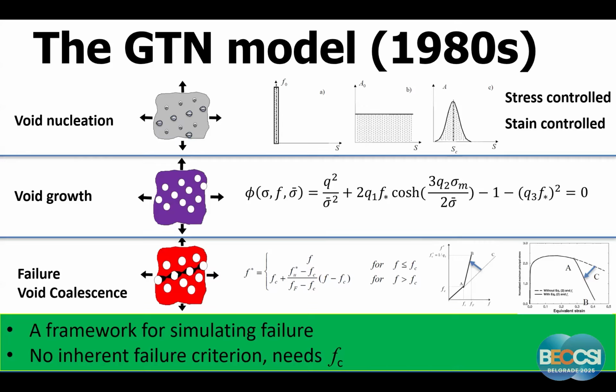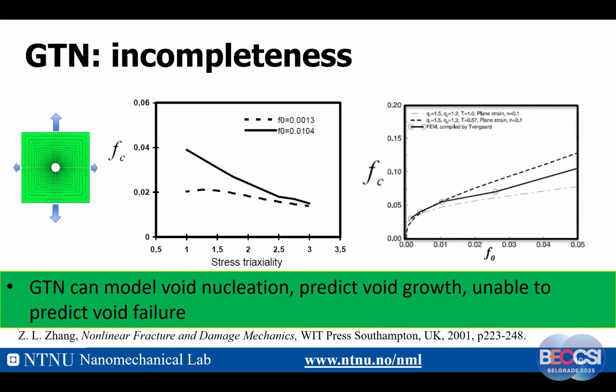Maybe it's confusing, but let me explain a little bit more. FC indeed was assumed by Tvergaard-Needleman as a constant. But it turned out that it's not constant. I used the Koplik-Needleman data and I found that FC depends on the stress triaxiality, and depends on the initial void volume fraction. That means it's not correct to assume FC is a constant. So my conclusion is that GTN can model void nucleation, can predict the void growth, but is unable to predict the void failure. So it's not complete. There is an incompleteness problem.